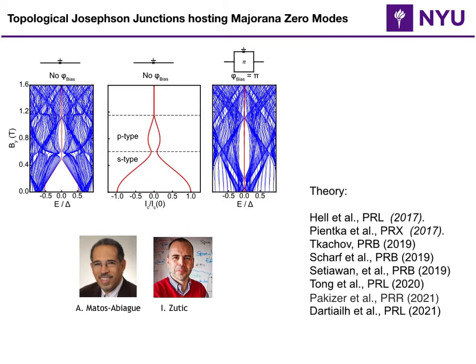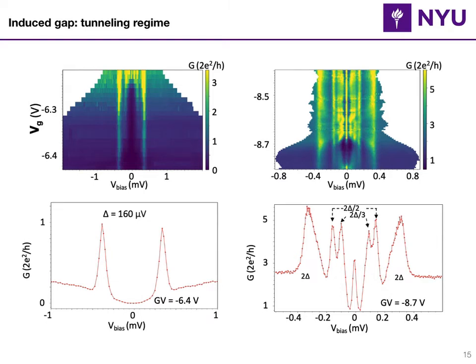But if you have a junction like this and you can phase bias it at pi, then in a no-disorder system, presumably the Majorana states at zero energy will start at very, very low field. And that's another way to actually create this. So in this talk, I will mainly stay with the left picture, where we do not bias the junction, but we use a SQUID loop to measure the phase of the junction as it transitions from S-wave to P-wave.